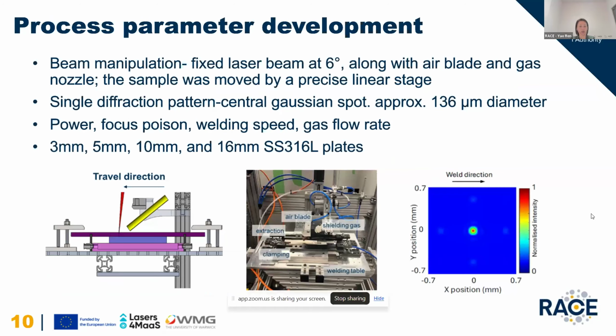So after several trials, this is our final setup we used for process parameter development. We have the laser beam set up at a 6-degree inclination angle impinging on the material surface. And here, this is a tailored shielding gas setup together with the integrated air blade, which is mounted to the table. During the welding, the table moves with the laser beam fixed. And for all the trials, we use a single pass. The laser beam was at 136 micron diameter, which is really small.